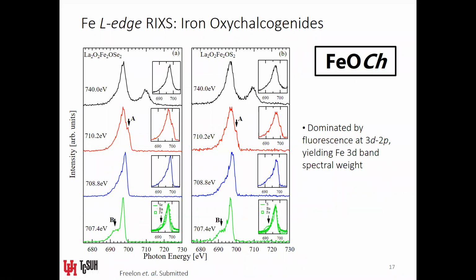So these are features that show up because we are exciting electrons into the unoccupied density of states, and the downward transition is emitting X-ray photons that are from this lower Hubbard band feature. So we do that, and we see that in both of our two different versions of the iron Mott insulators that we have: the selenium version on the left, the sulfur version on the right.